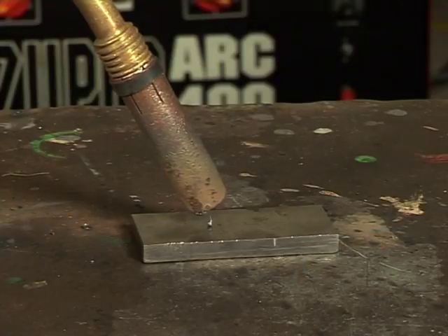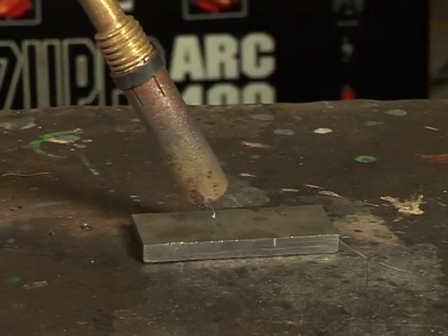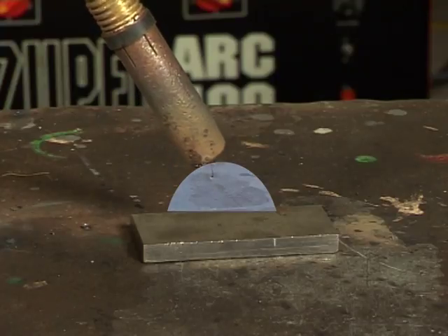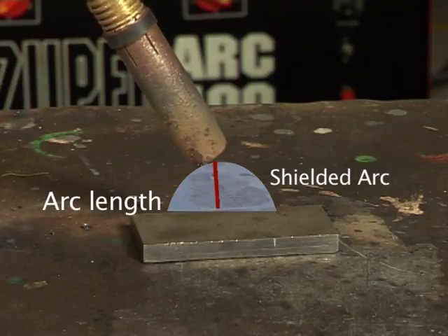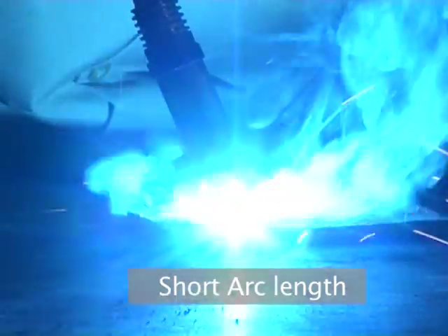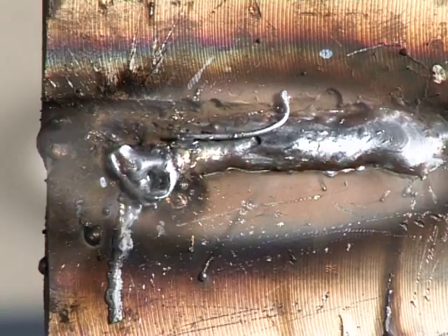The distance between the metal surface and the tip of the electrode is called arc length. Adjust the current and voltage individually. If the voltage is too low, the wire sticks to the base metal, generating cracking sounds, and no arc is produced. If the voltage is too high, the wire burns, arc length becomes long, and much spatter is generated.